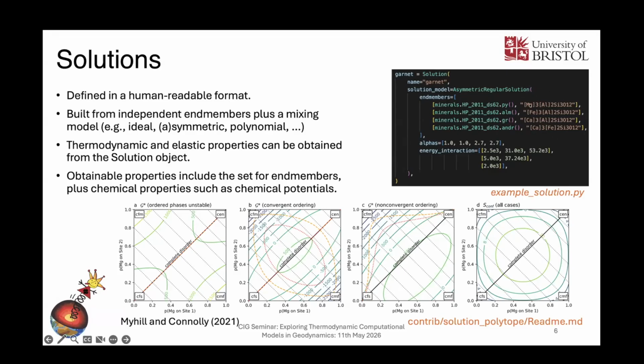So basically the square brackets here dictate which different species sit on each one of the different sites. And the number after those square brackets gives you an indication of the multiplicity of each one of those sites. And then within that single expression, that gives you the ideal entropy of mixing for those solutions.